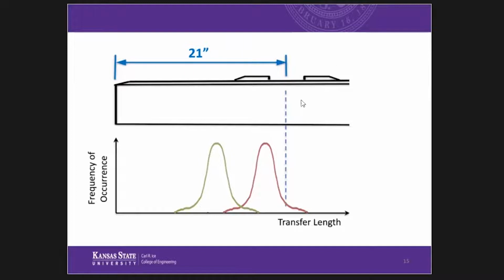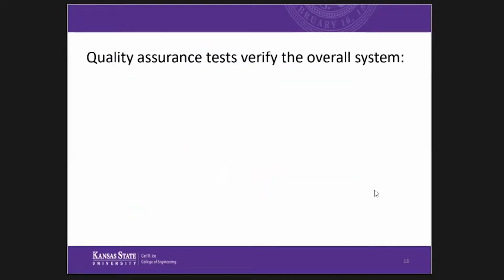Even though there's a chance, because there are some tails that exceed 21 inches, but by and large, it's going to test the same. But this stands a risk of some of the ties we produce not having the moment capacity we want at the rail seat. Likewise, our distribution could be on the short end, which is going to tend to result in higher bursting stresses. And so how do we determine where we are?